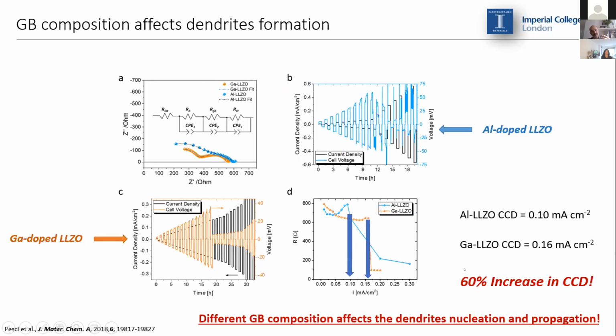So by doing this experiment and by showing you this result, I've just shown you how different grain boundary composition can affect the dendrite nucleation and propagation. And so how, if we change the grain boundary composition, we can actually target an engineering of the material.